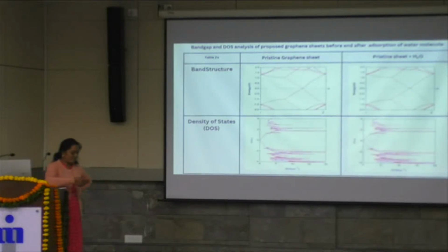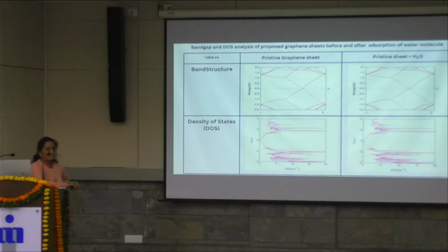Initially, when we checked with the water molecule, what we observed was that the band structure was the same, as well as the density of states. There is no change because it is not reacting with the water.